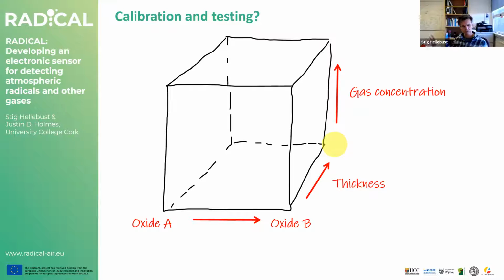So if I take you through some of the tests we've done with the oxides that Justin explained, we have native oxides, we have thermally grown oxides, and different thicknesses. So we might measure a set of features on one of those oxides. Let's say the native one first. You change the oxide layer and do the same test, and you get a different set of features. That's fine. And then you try a different thickness of that layer, and you will get a different set of features. But the features will not necessarily change in the same direction. Some of them may not change at all.